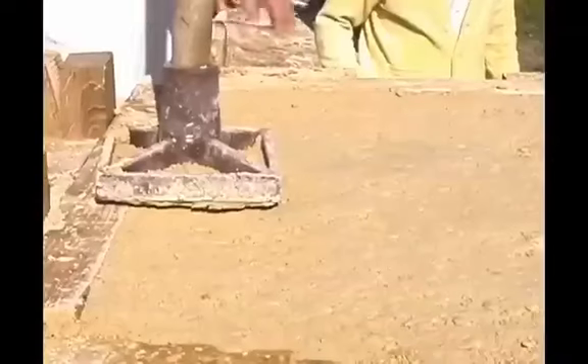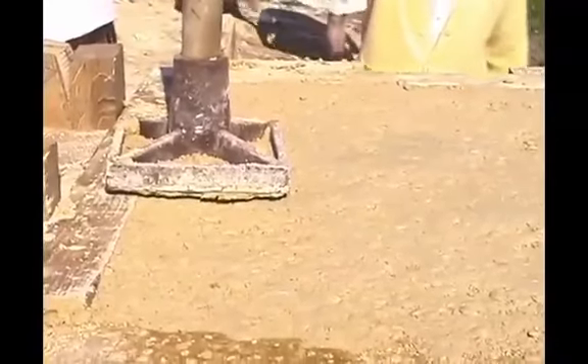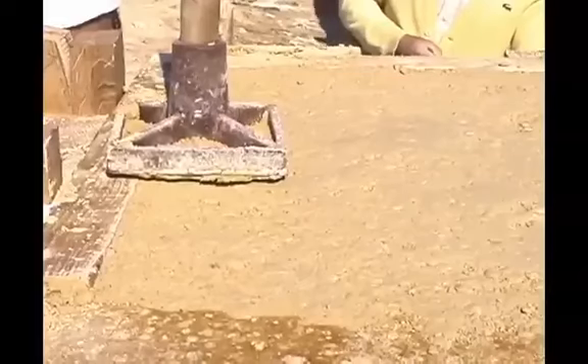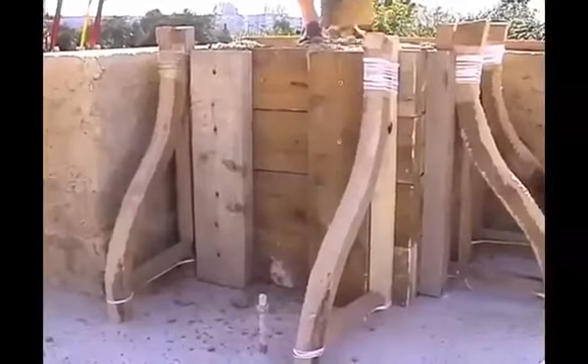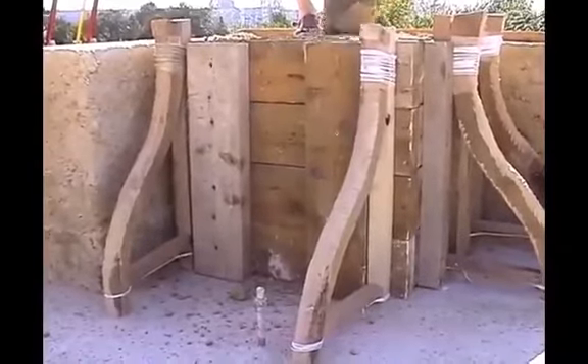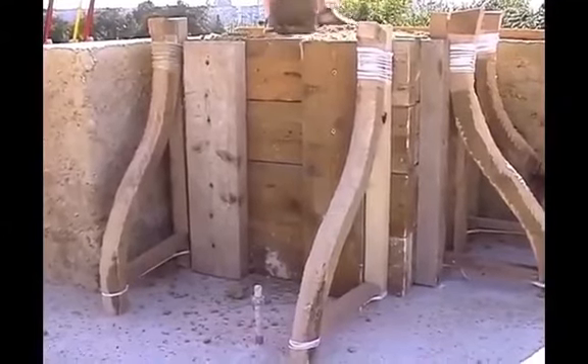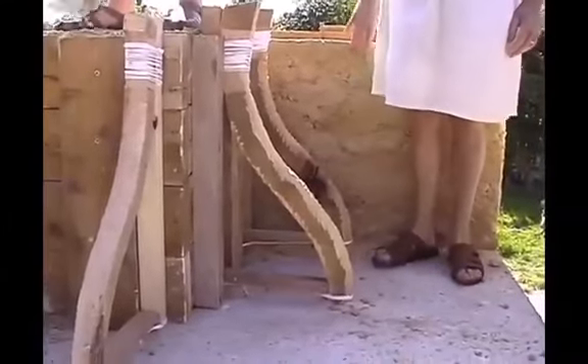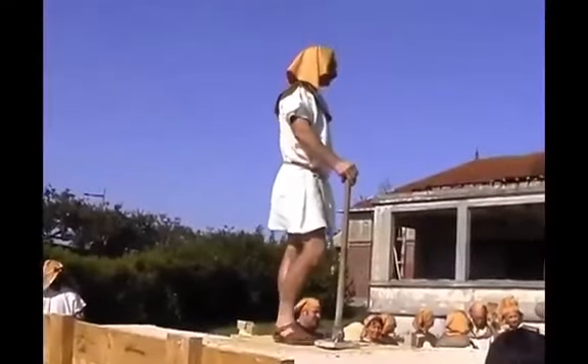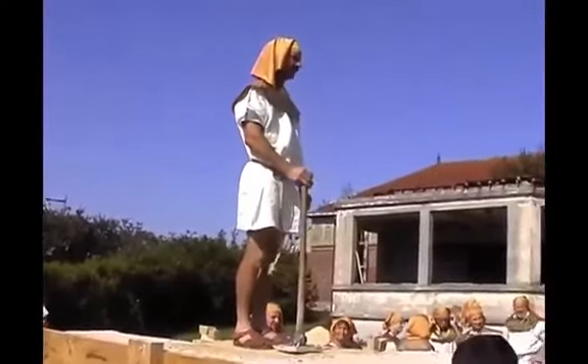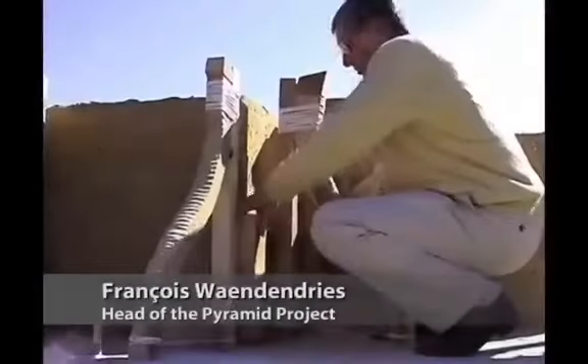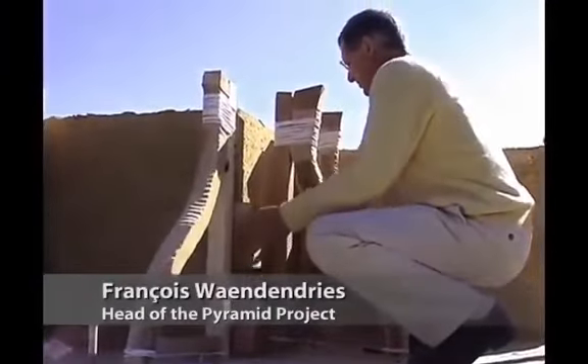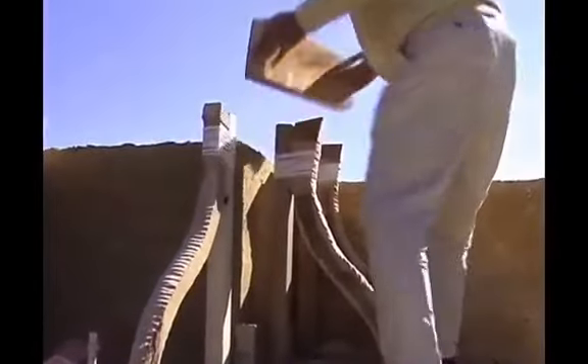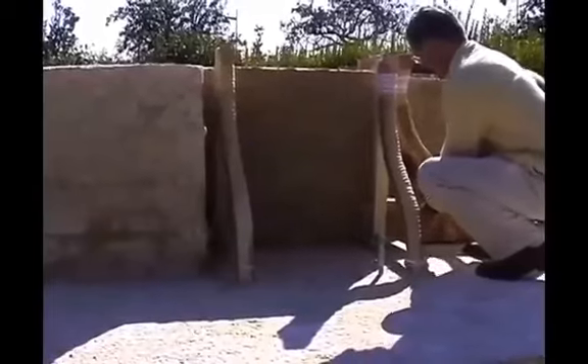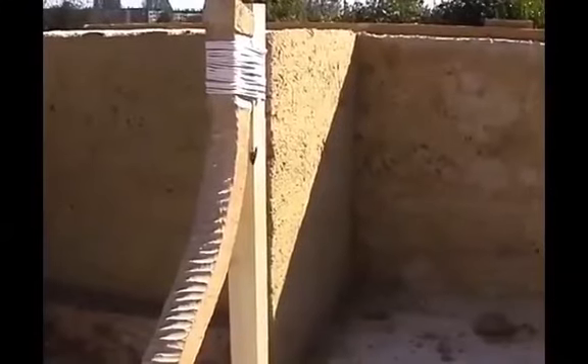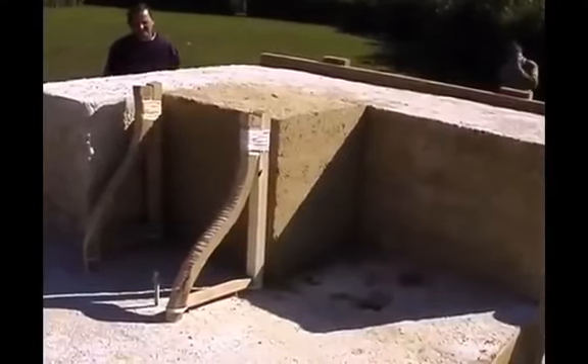When the climate is warm and beautiful, our crew rapidly produces a reagglomerated limestone that proved strong, dense and true to the plan's size and shape. The mold consists of small wooden boards, which can be reused many times for making other blocks. In this ideal weather, the whole process runs smoothly and is very simple. We remove the mold 4 hours later. The synthetic limestone looks like a natural stone. We observe no trace of wood grain.